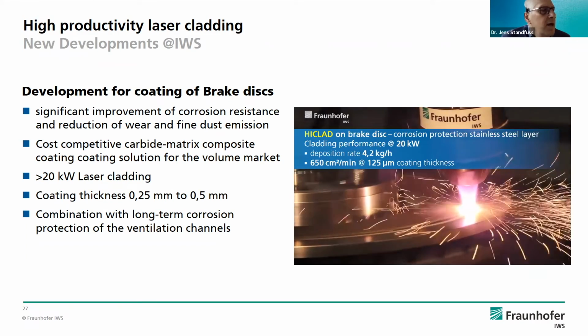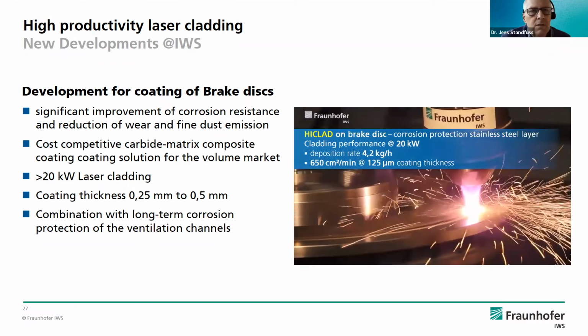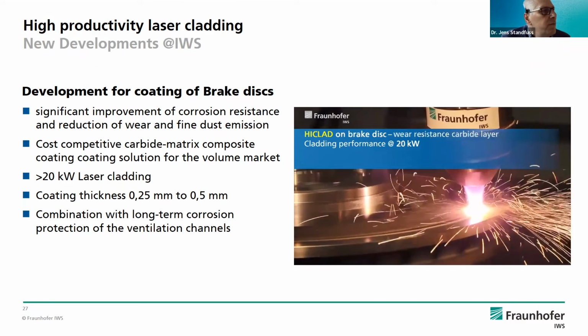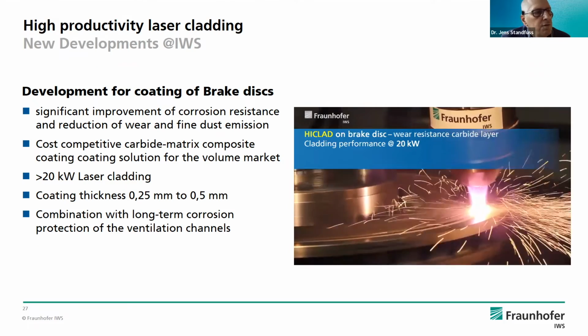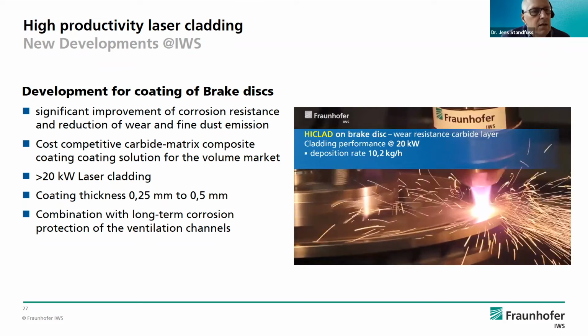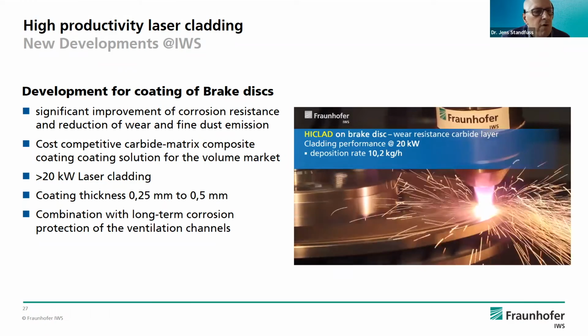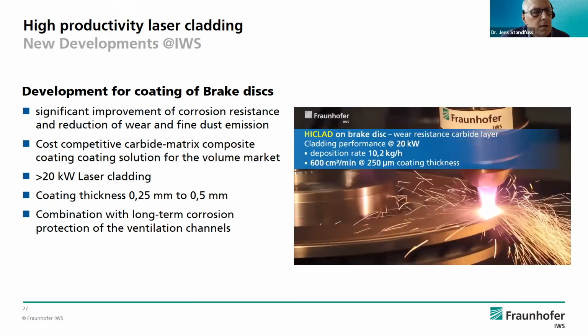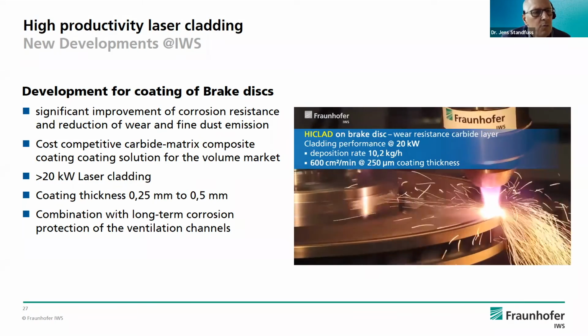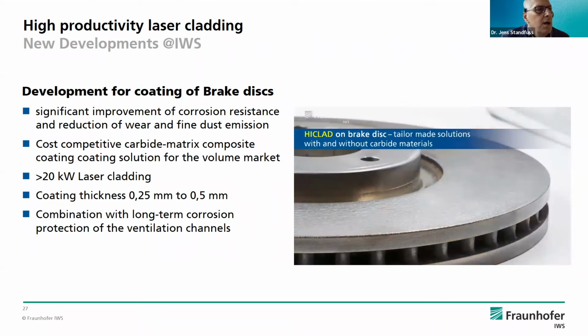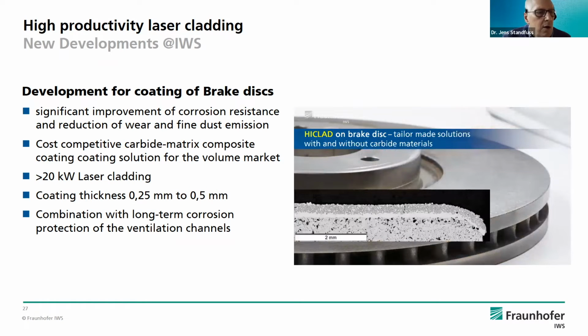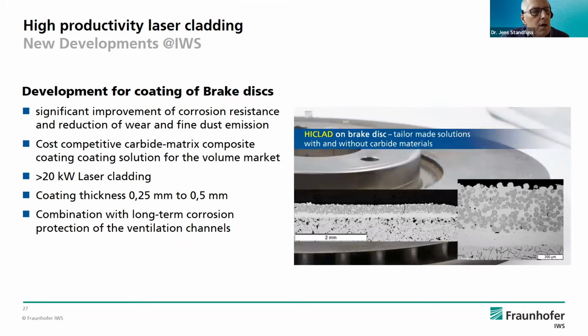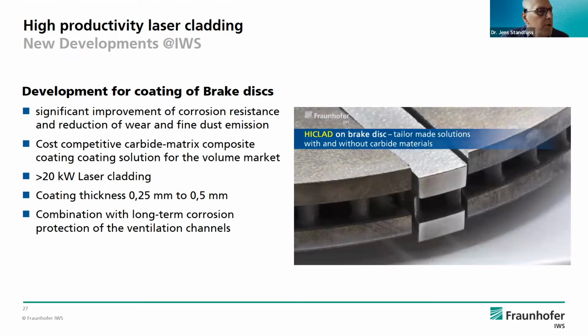With these coatings, you can cover the risks or improvements which are needed. This comes from the corrosion resistance, where you need an improvement, and the reduction of wear, and especially the reduction of fine dust emissions with respect to the environmental requests, which are getting harder and harder for the automotive industry. At the end of the day, it is a tailor-made solution, with or without carbides, where you can adapt the composition of the cladding layer to the requests of the part.